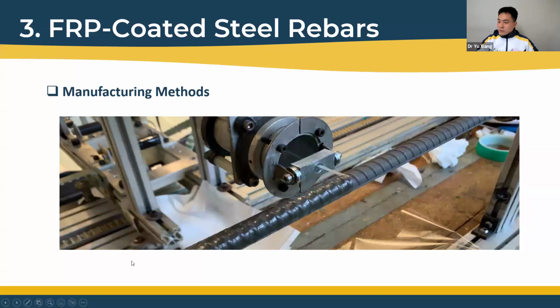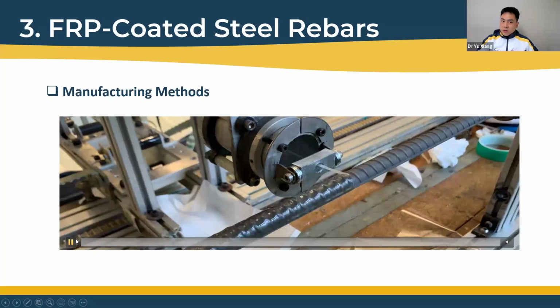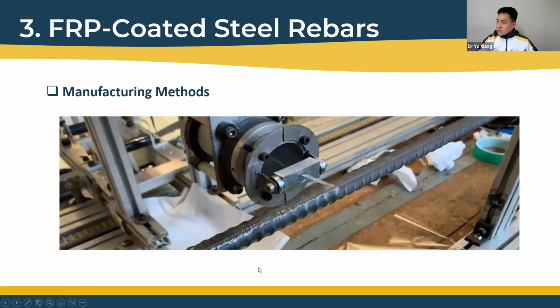Our group has developed 2 different manufacturing methods for different quality requirements. The main procedure includes pre-treatment of steel, filament winding of the FRP coating layer, curing and hardening of the coating, and surface treatment. Here is a video showing the filament winding step.